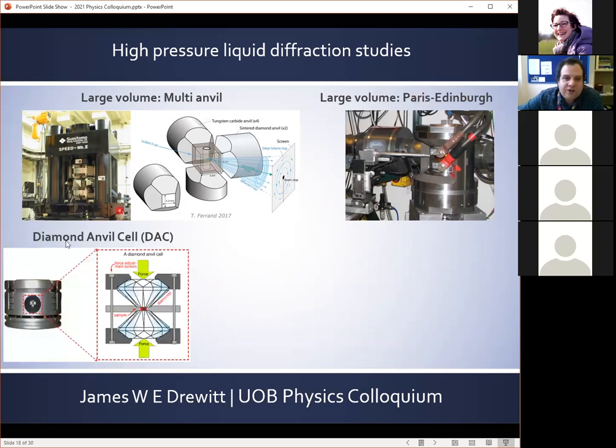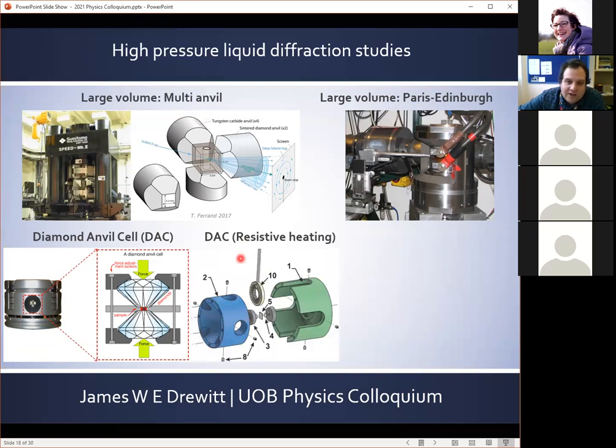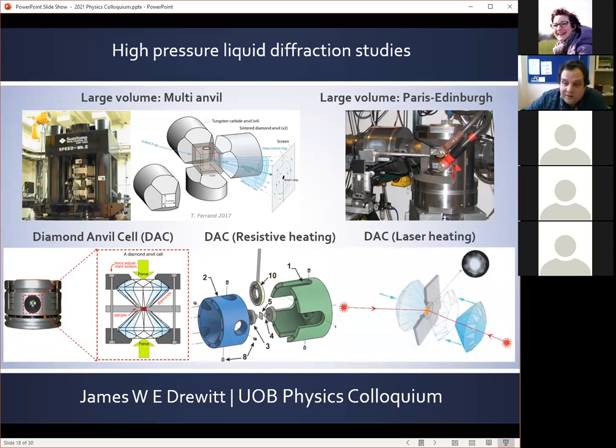However, for very high pressures, we need to use the diamond anvil cell. And actually, the diamond anvil cell has advantages in that the diamonds are relatively transparent to X-rays and optical wavelengths, so we can monitor the behavior of materials in situ using X-ray diffraction or optical spectroscopy techniques. And we can heat our sample in a diamond anvil cell by equipping it with resistive heaters, or using laser heating, where we pass infrared laser beams through the transparent body of the diamond to heat our sample under compression.